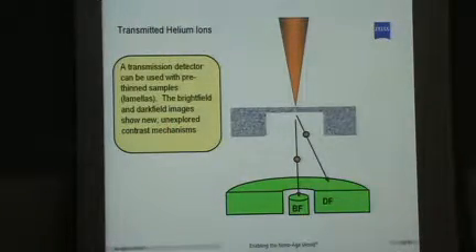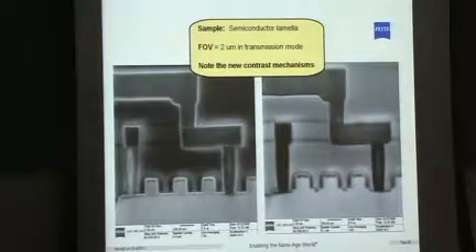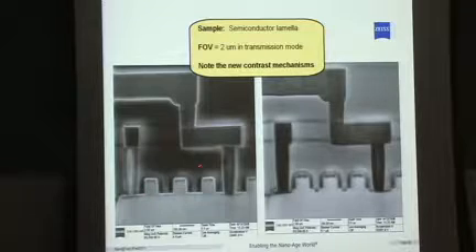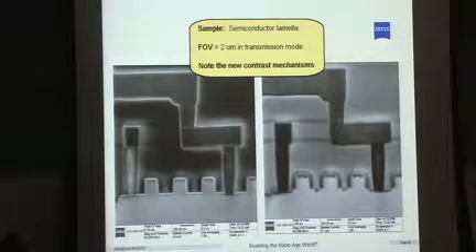But there are other imaging modes that we've started to explore. One of them is looking in transmission. There are transmission electron microscopes. We tried it with the helium beam. We made a very simple detector, a bright field and dark field. We got some very thinned out samples, and we looked at them. And what we found was there's some really unique contrast mechanisms in these very thin samples.